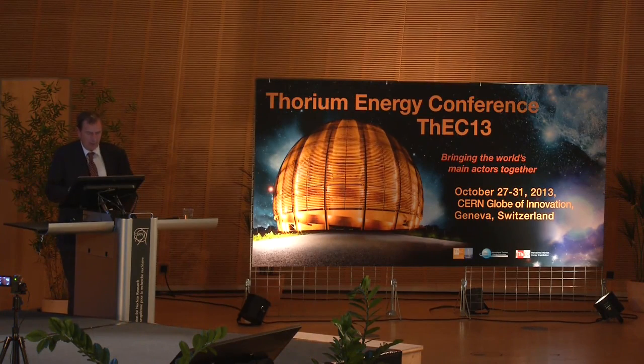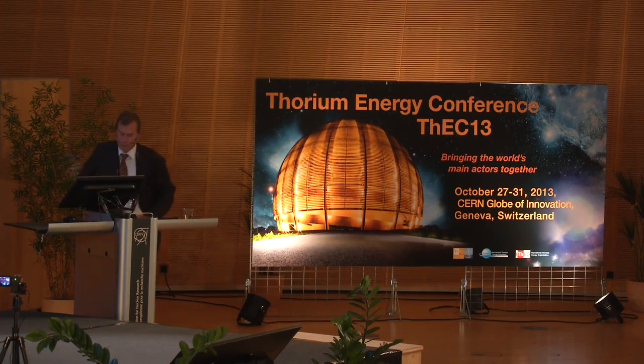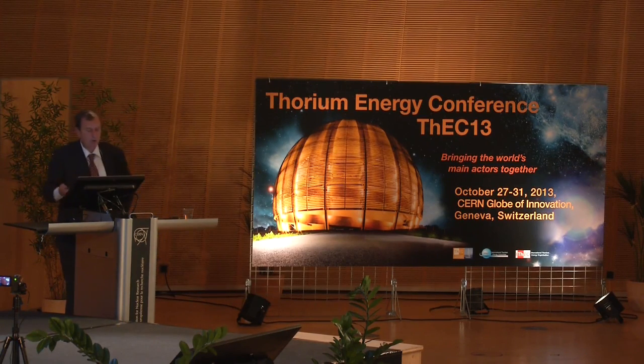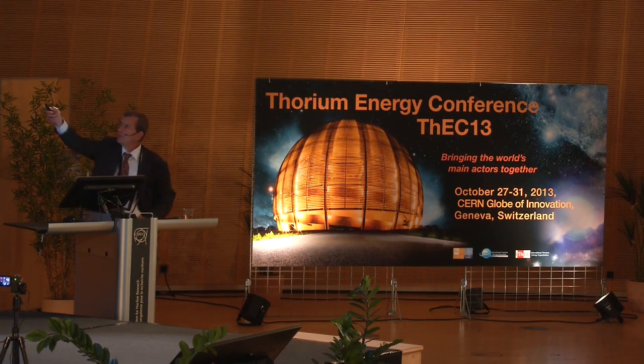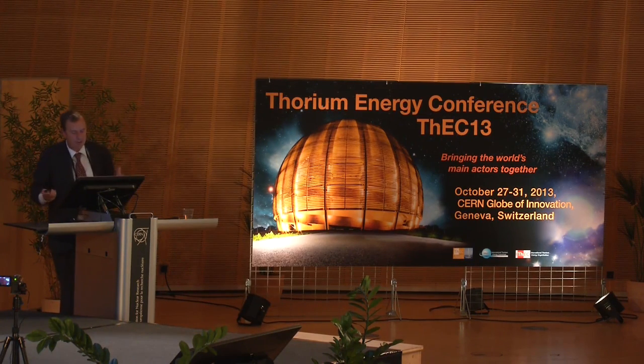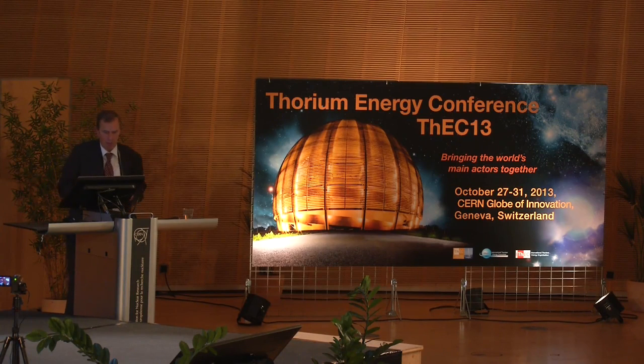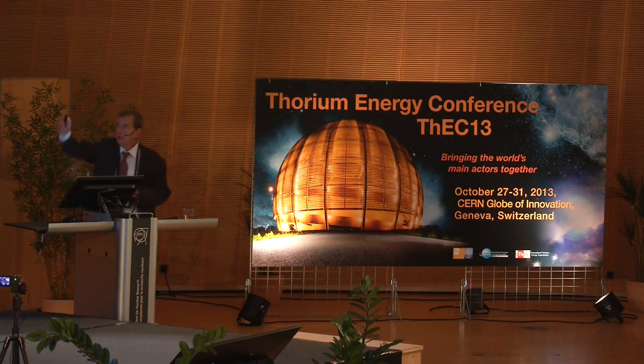Now this is the same, but it shows 2 graphs. One graph is on the right side, a little bit the same as before, but thermal conductivity. And as a summary, at 1000 degrees Kelvin, the thermal conductivity of uranium MOX will be between 3 and 3.5, thorium MOX above 4. This gives you the range of improvement of the thorium. But I have another remark. It is on the left side. This is only considering MOX fuel, uranium, plutonium. And the curves can be different also, not very much, but okay, in a range of at least 10%.